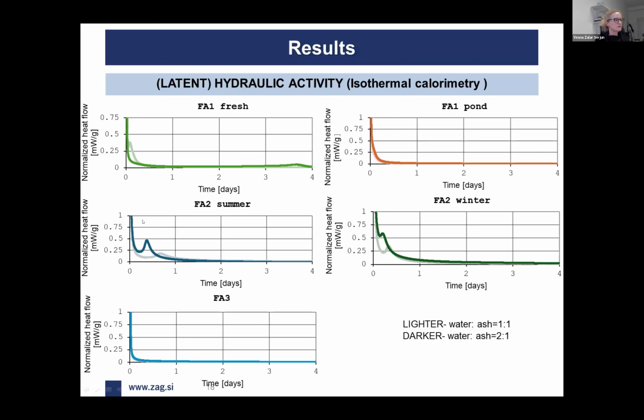So the lighter colored lines present the pastes with ratio 1:1, and the darker ones with ratio 2:1. For the ash Fa1 fresh, we can see that the heat release of the reaction can be detected relatively soon after mixing it with the water. On the contrary, when a larger quantity of water is added, this does not happen. In comparison to Fa1 fresh, Fa1 pond material does not show any heat release, meaning nothing is happening regarding the hydraulic reactivity.